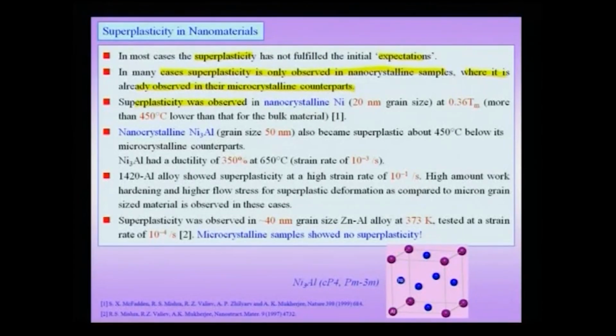For instance, there are materials which are antiferromagnetic in the bulk, but which will tend to become ferromagnetic in the nanoscale. So, these are very surprising effects, but in the case of superplasticity, in most cases it is seen that superplasticity is only observed where already in the micron scale grain size sample you observe superplasticity. Superplasticity was observed in nanocrystalline nickel with a grain size of about 20 nanometer at 0.36 Tm. That means it is about 450 degrees lower than the bulk material.